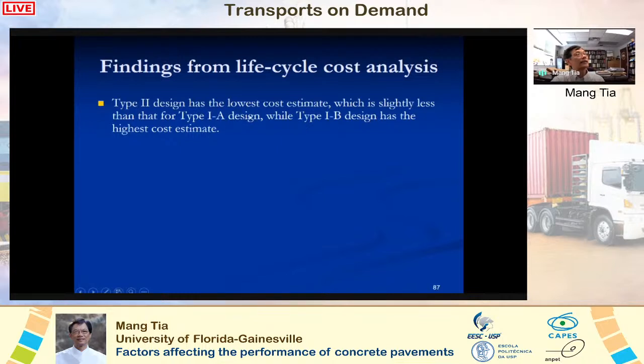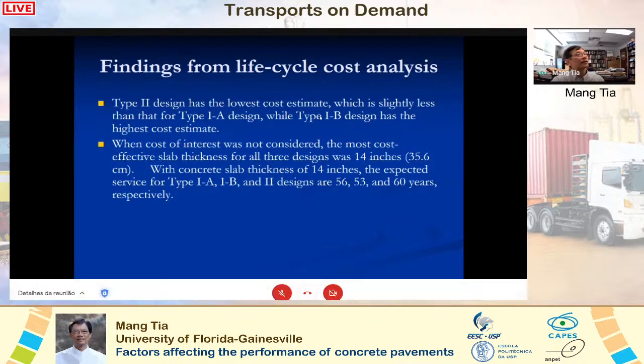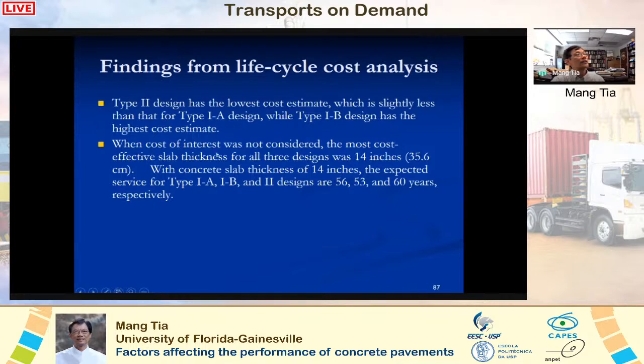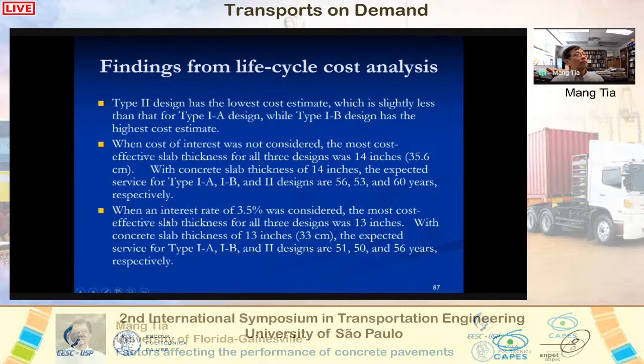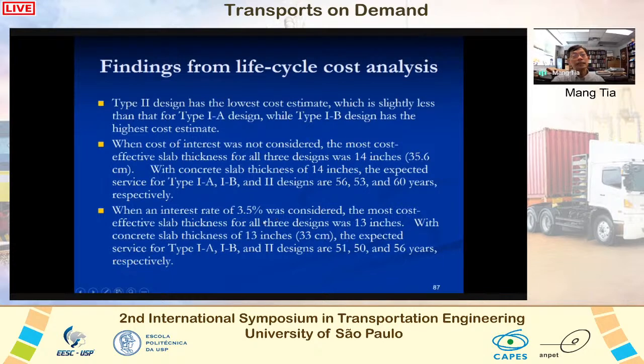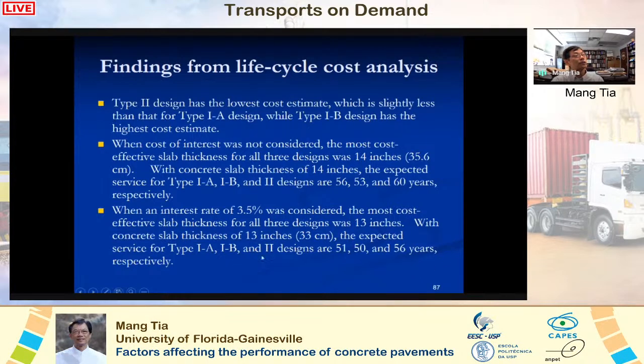Type 2 design has the lowest cost estimate, and when cost of interest was not considered, we can use much thicker slabs. But if we have an interest rate of 3.5%, then we can go with 13 inches, which is equal to 33 centimeters, and the expected life would be 51, 50, or 56, depending on the design. So design 2 is the best.